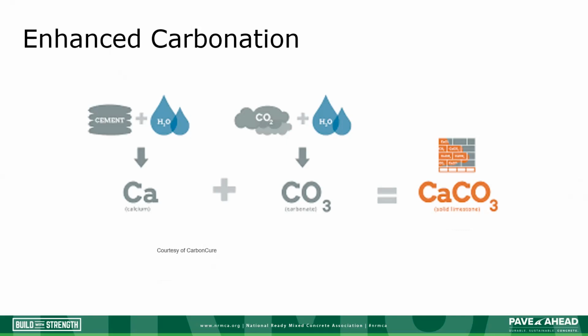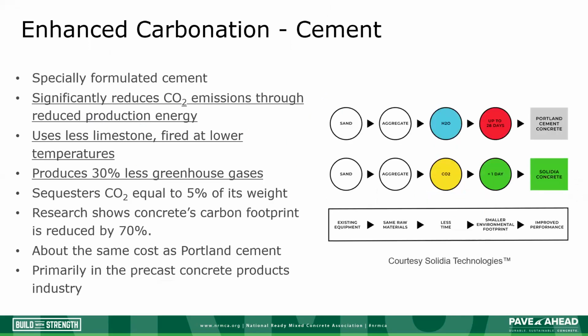In simplest terms, enhanced carbonation involves injecting CO2 into the cement, aggregate, or concrete, creating calcium carbonate, in effect, a synthetic limestone. And in the process, a small amount of CO2 is sequestered. Applied to cement production, enhanced carbonation has several positive impacts, including lower resource consumption and lower manufacturing temperatures, which in turn result in reduced energy consumption during production, reducing greenhouse gas emissions by 30%, and can reduce concrete's carbon footprint by as much as 70%.